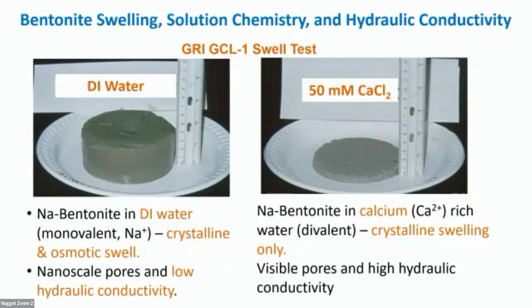And if we pour deionized water on top of that bentonite, it swells like crazy. This is what we'd expect for bentonite that we would use for lots of sealing applications. In fact, it starts off about 6 millimeters, and you can see this has swollen up to on the order of 40. So it just swells like crazy. Extremely impermeable. Take that same granular bentonite and hydrate it with a 50 millimolar calcium chloride solution.